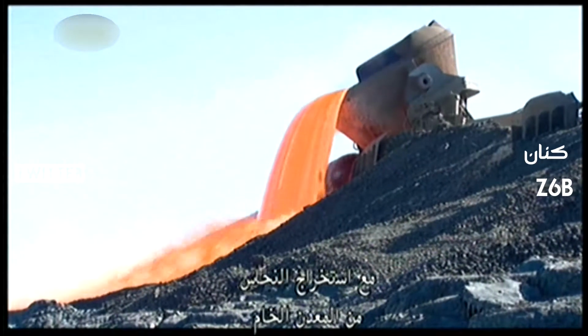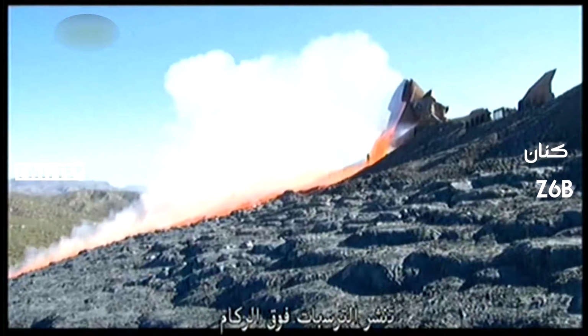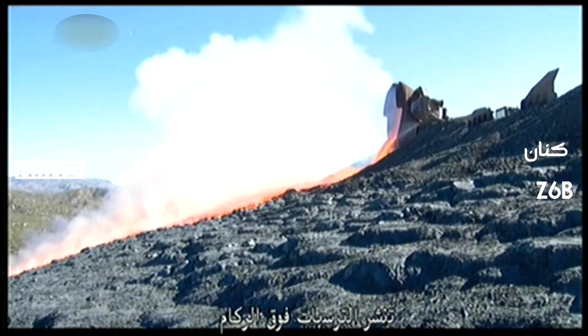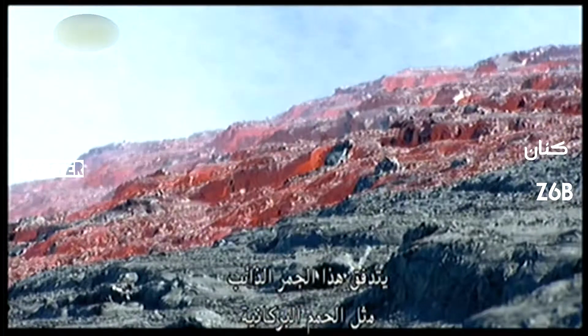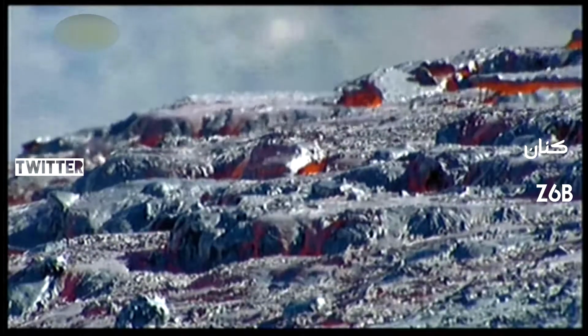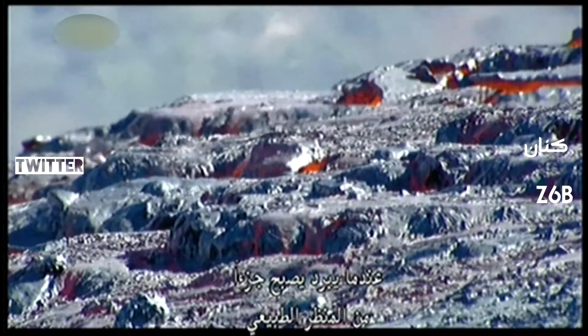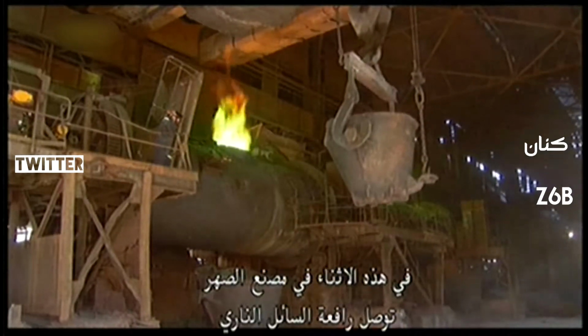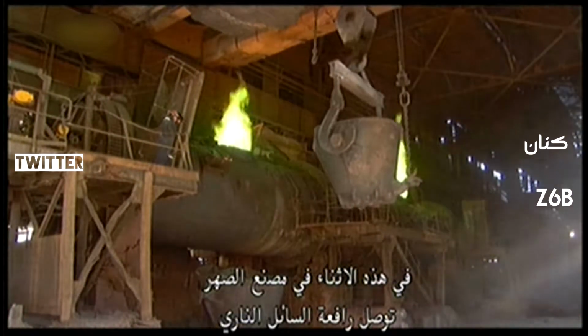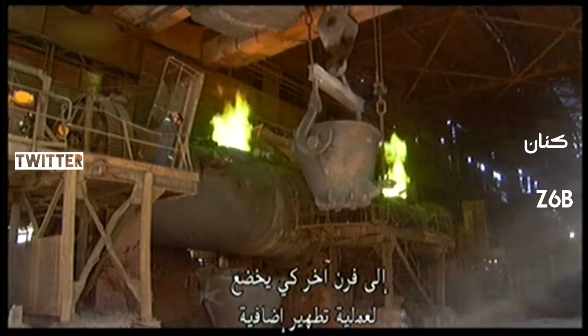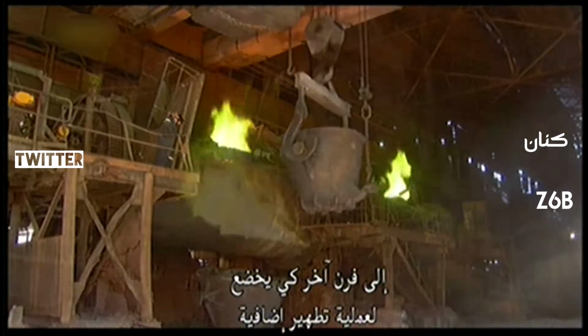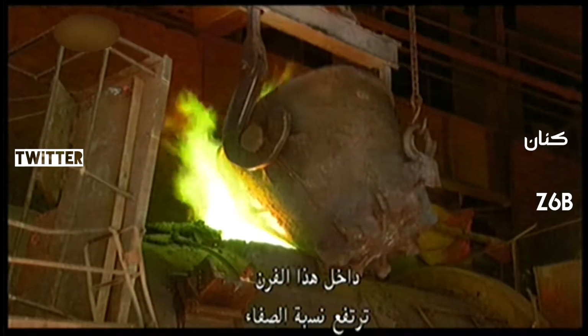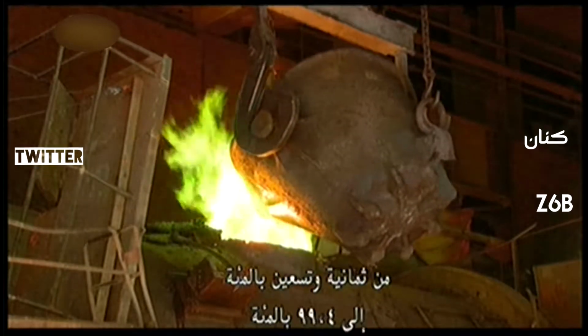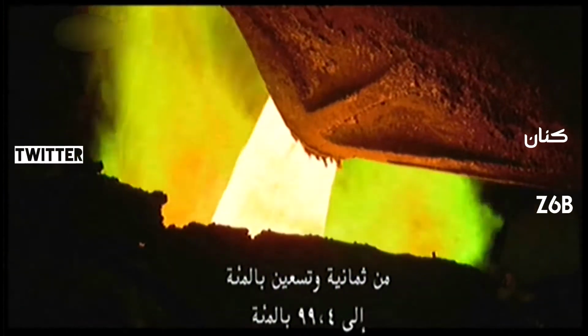With the copper now extracted from the ore, the residue is poured onto a heap. This molten slag flows down like lava from a volcano. As it cools, it becomes part of the landscape. Meanwhile, in the smelter, a crane delivers the fiery liquid copper into another furnace for further purification. Inside this furnace, the purity level increases from 98% to 99.4%.